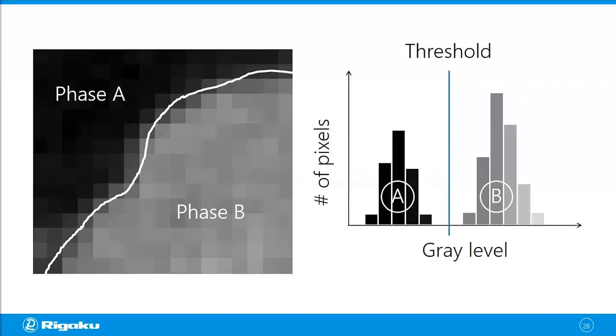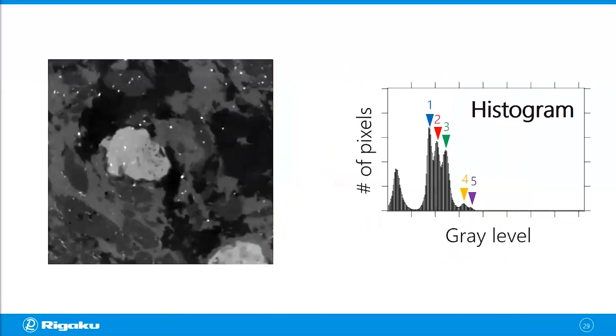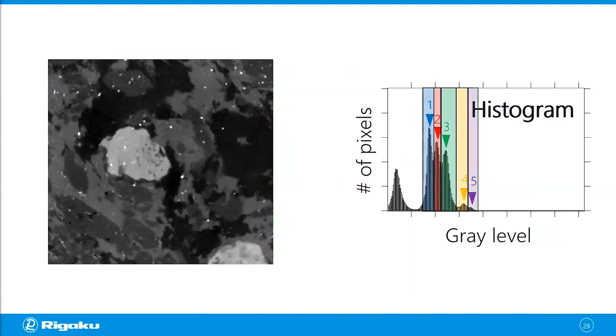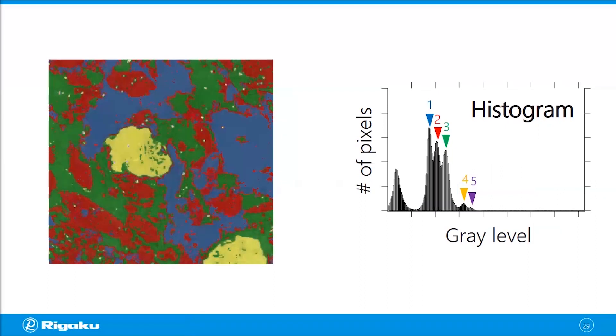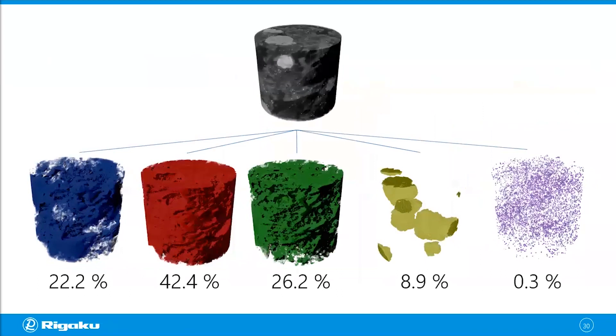You can see how handy a histogram is when trying to segment images into different phases. Now let's zoom out to see the big picture. This sample has five phases — one peak is coming from the air outside the sample. For those five phases you can set multiple thresholds and map all those pixels back to the original image. Now you've segmented this image into five different phases. You can do this for the entire volume and then calculate volume percentages.